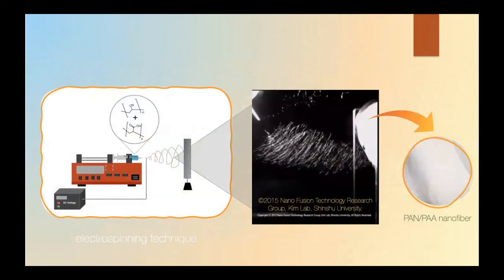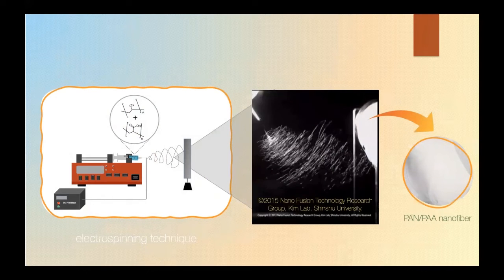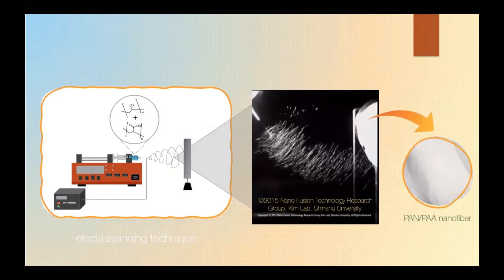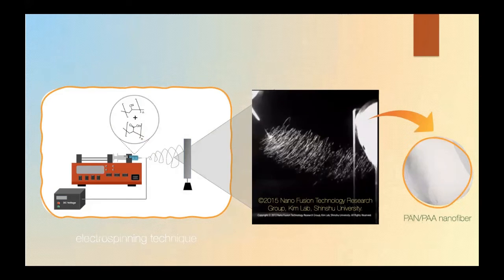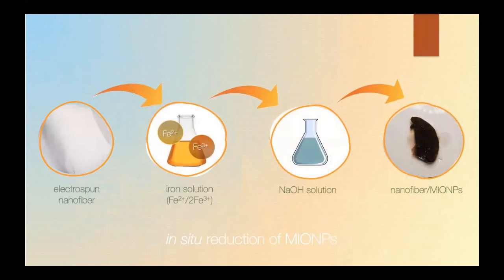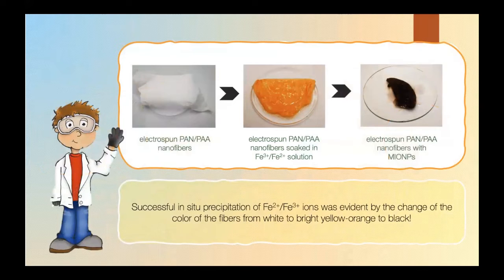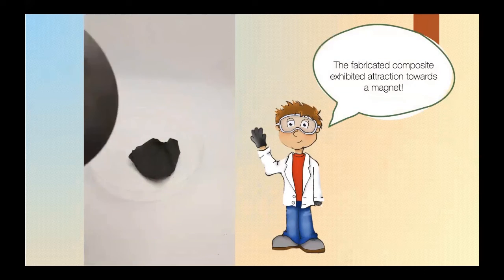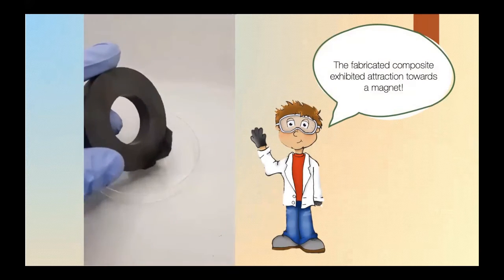To realize this goal, we employ electrospinning technique to obtain nanofiber sheets from the blend of polyacrylonitrile and polyacrylic acid. Afterwards, in situ reduction of iron ions on the nanofibers was done by subsequent soaking and alkaline treatment of the nanofibers. The successful precipitation of ferric and ferrous ions was evident by the change of color of the nanofibers from white to bright yellow-orange to black. The black color indicates the presence of iron oxide on the surface of the nanofiber.